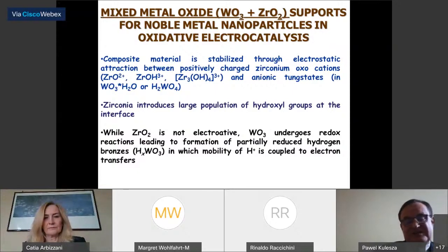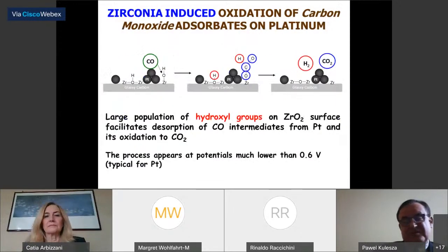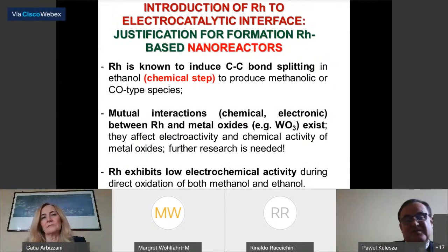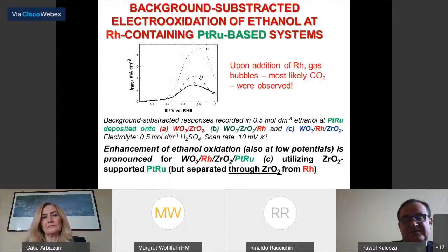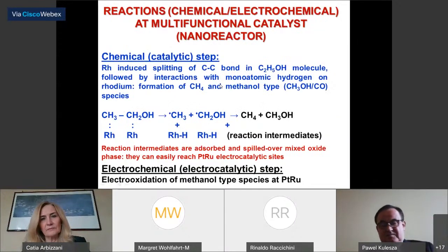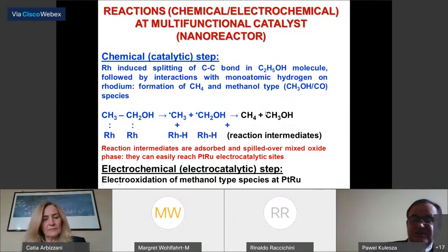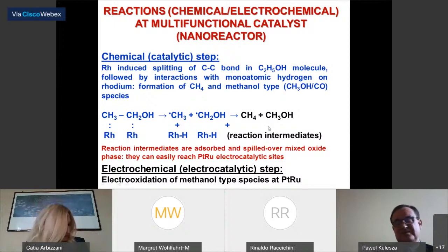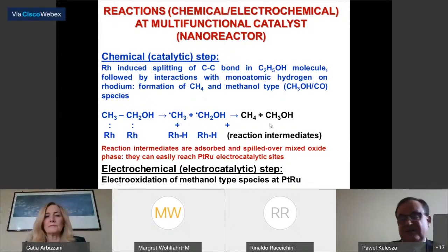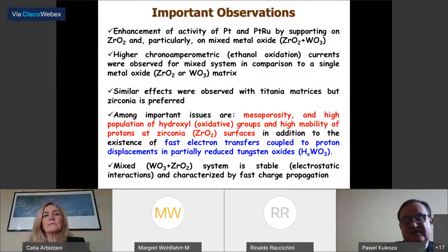Later we use mixed oxides of tungsten oxide and zirconia, highly protonically conductive. We can introduce hydroxyl groups, and added rhodium, which breaks the C-C bond, and briefly speaking, we can observe enhancement. The model is that rhodium can break the C-C bond, but the actual reaction is continued on platinum ruthenium. This was done in Ivona Rutkowska's laboratory later.